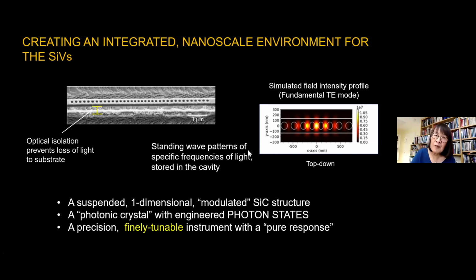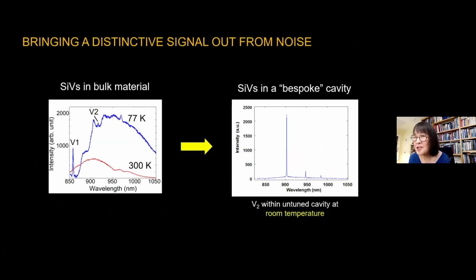Now, to give you some indication that this works, that we indeed can bring signal out of noise by building this very bespoke, that is, particularly generated, uniquely distinctive environment that we design for the silicon vacancy within. If you remember the photoluminescence spectrum I showed you at the beginning, even at low temperature, we could hardly distinguish the signal from the silicon vacancy from the background noise.